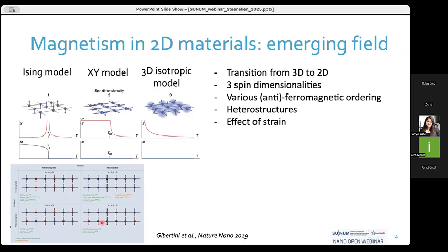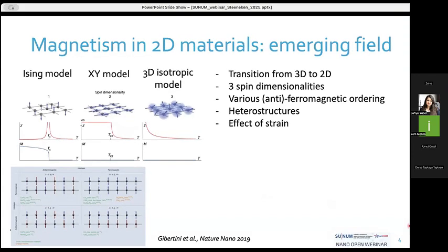The type of antiferromagnetism that occurs depends both on the magnetic coupling between the spins in 1 layer, but it can also depend on the coupling between the spins in different layers. Those spin coupling strengths are indicated by the letter J, and they can depend on the type of material, but also on the distance between the layers, for example.